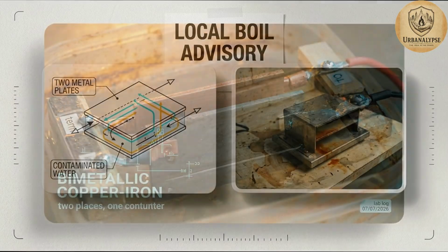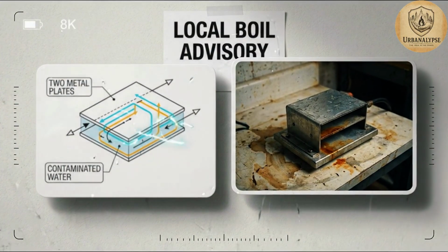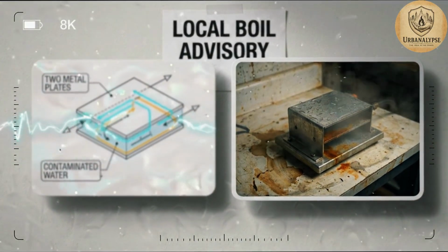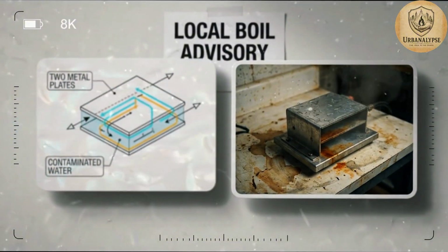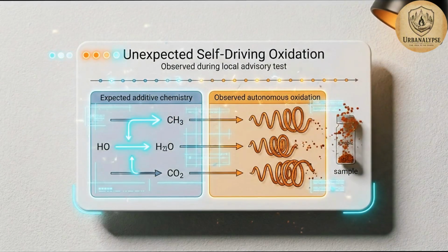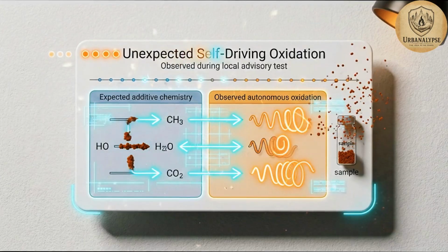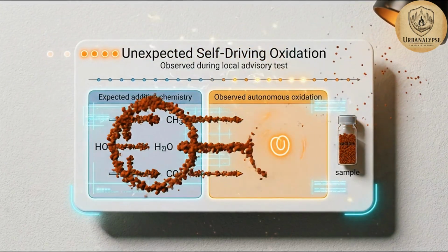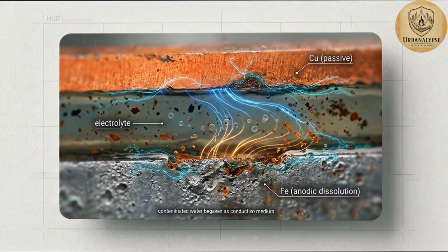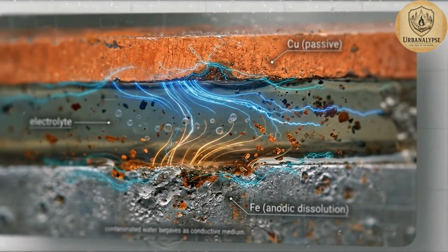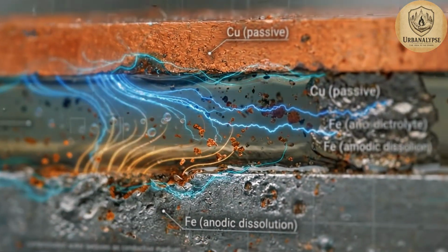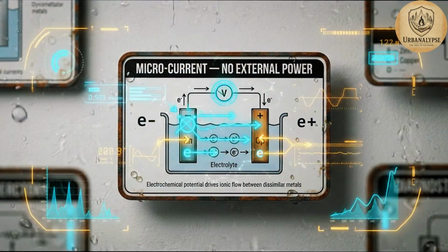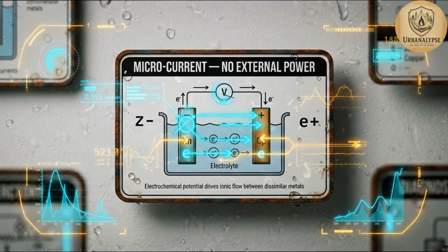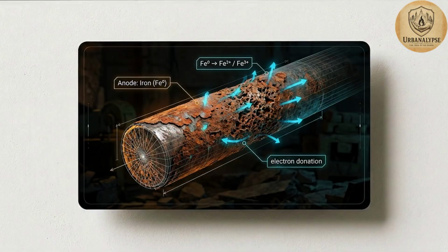Bimetallic copper-iron galvanic cells. I built a test rig for this. 2 plates, 2 metals, 1 container of contaminated water during a local boil advisory. Expected additive chemistry, got a self-driving oxidative process I hadn't fully accounted for. When copper and iron share an electrolyte, which is what contaminated water is, the electrochemical potential difference drives a microcurrent without any external power source.